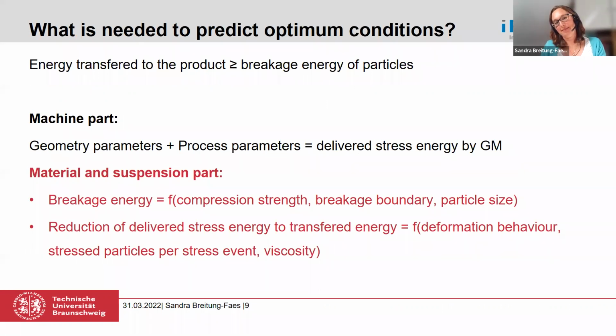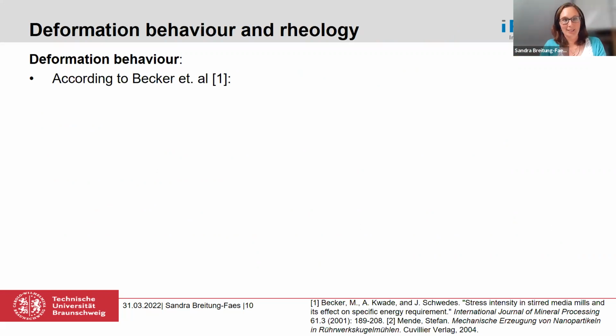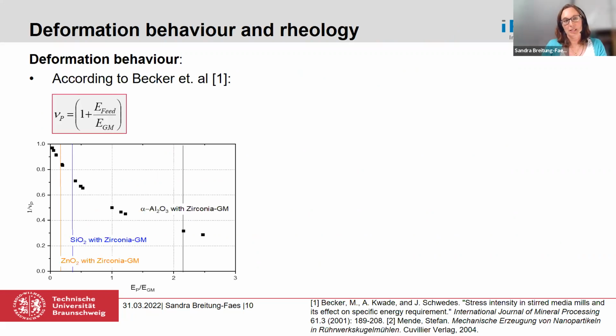Where I would like to show you at least what I think about the material and the suspension part, and how I rearranged or enhanced the model with some material parameters. And there I also had the luck to have somebody else who did already some work on it. This was Michael Becker, who was also working for Mr. Schwedes, and he introduced at least something like an energy transfer coefficient for the product, which is recognizing the deformation behavior of the product to the grinding beads. And when you introduce it into the stress energy, you would take the reciprocal value. So you can see it here on the y-axis. And I plotted it here over the ratio of the Young's modulus of the product and the grinding beads.